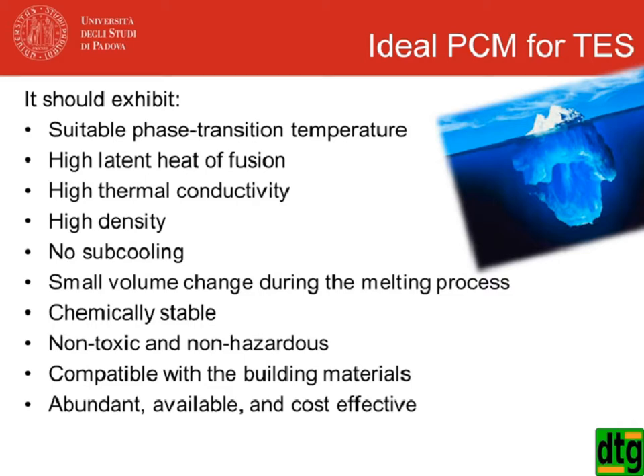What about the thermal conductivity? It should have high thermal conductivity. Okay, to clear away any doubt, none of the available PCMs shows a thermal conductivity which is high enough. Usually, the thermal conductivity of the PCM is extremely low. Of course, it should present high density. Considering the highs, more than 1,000 is good. Below 1,000 is not that good.